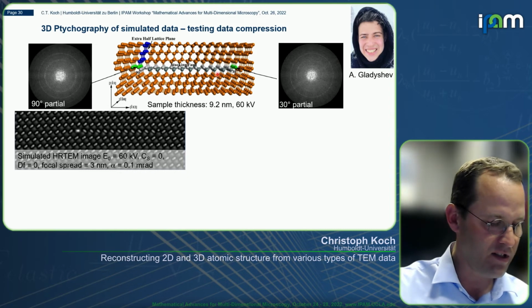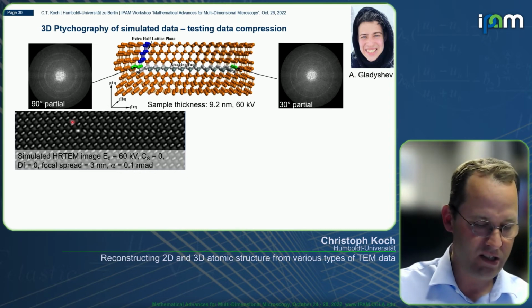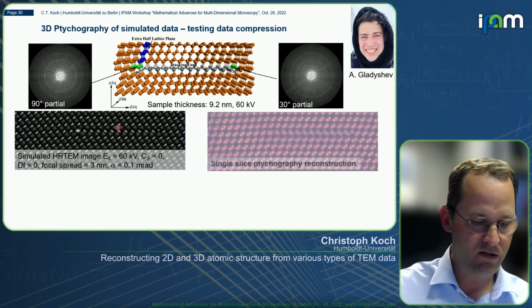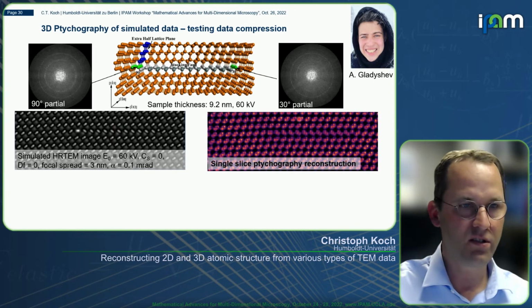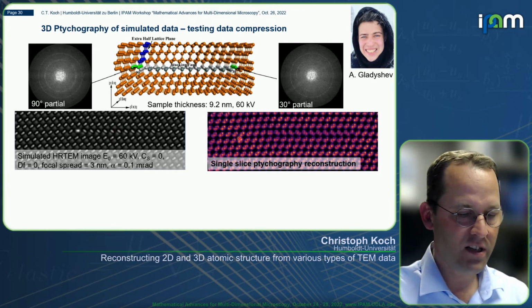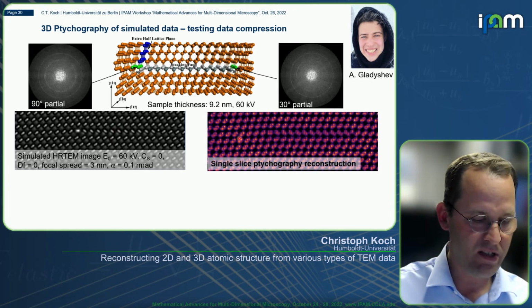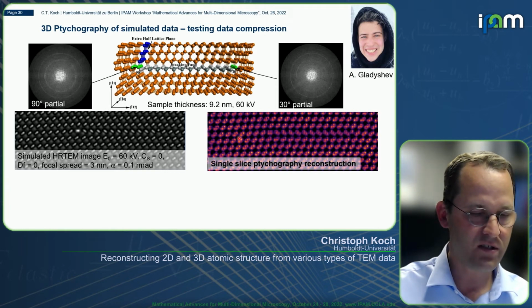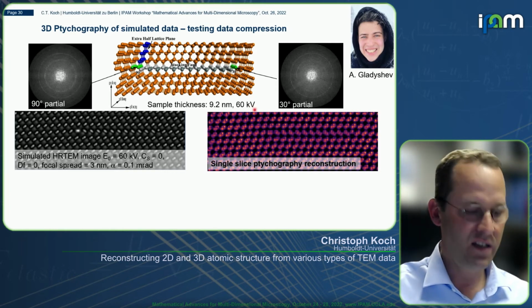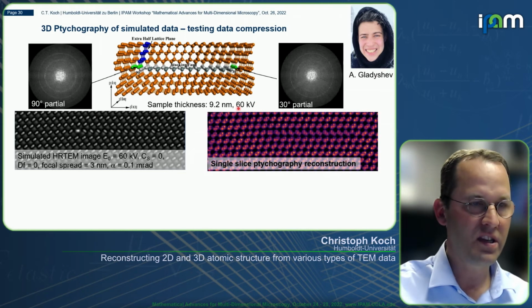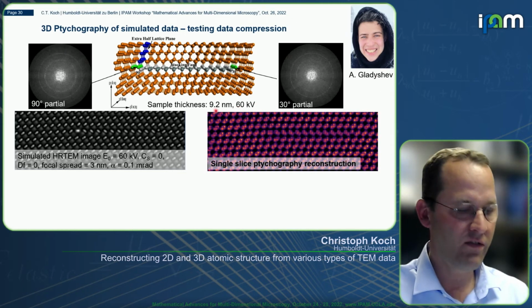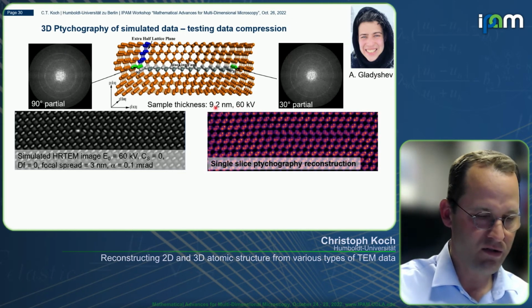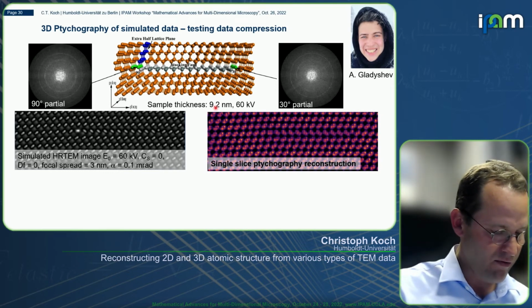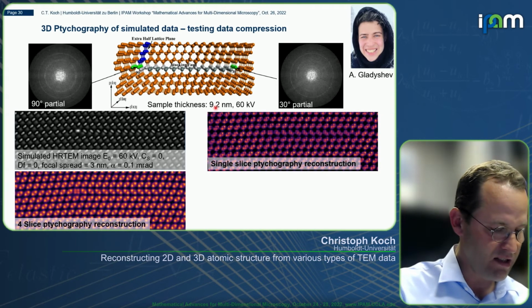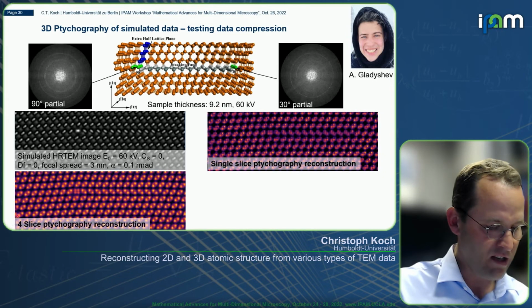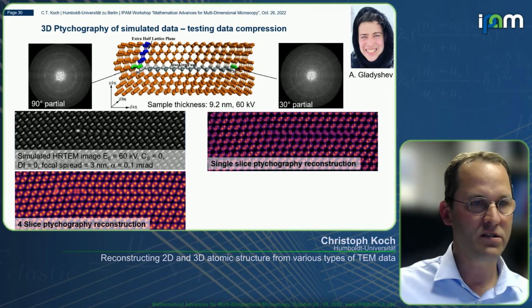And here you can see a high resolution image being simulated. Here you can see a single slice ptychographic reconstruction. Actually, you don't really see the atoms very nicely. And the reason is because the accelerating voltage was set to 60 kV. So this is, even though the sample is only 9 nanometers thin, 60 kV is a very low accelerating voltage leading to strong multiple scattering.